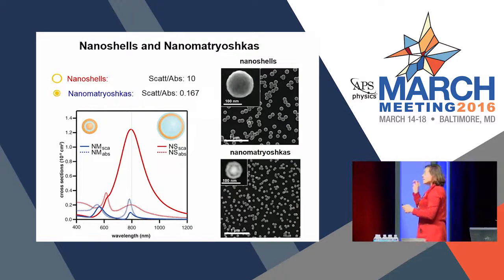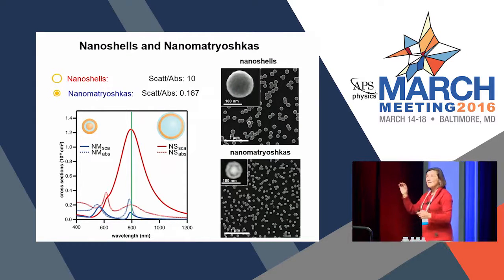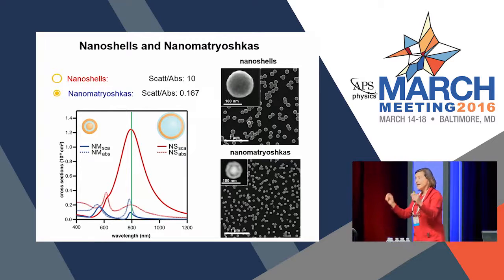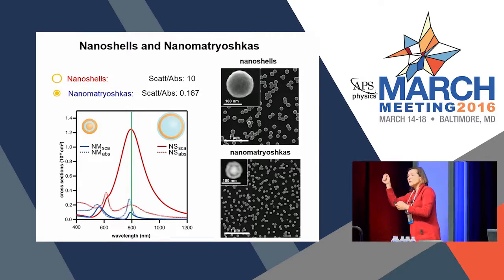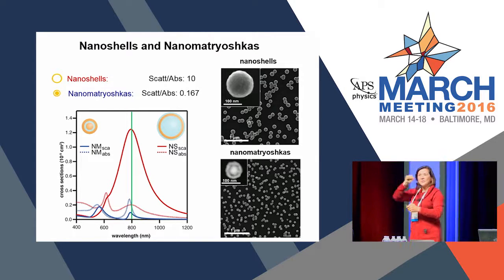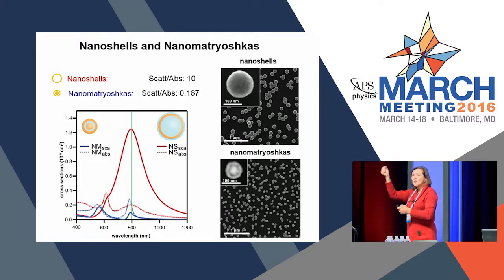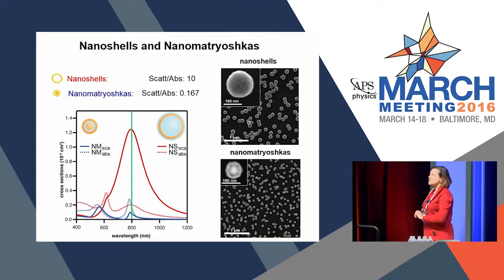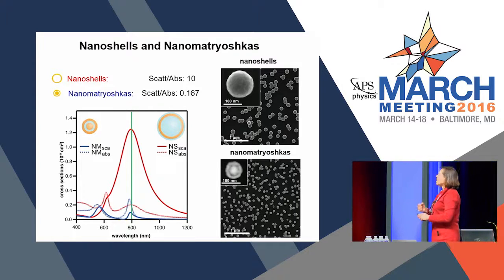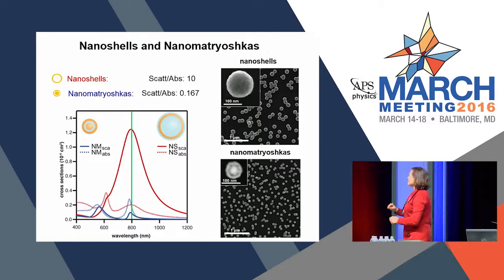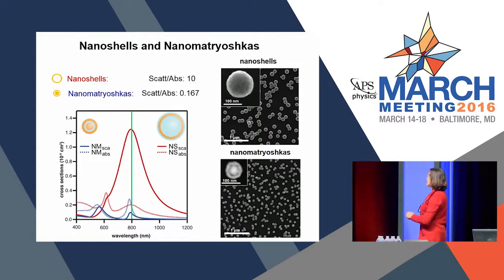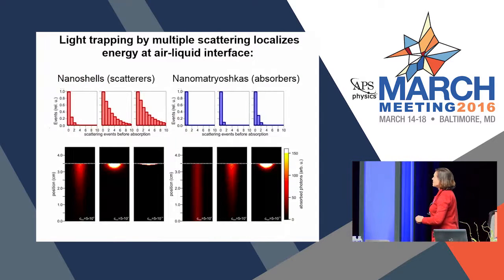To test this, we did a laser experiment, and we designed 2 different nanoparticles that had identical absorption, but depending on the properties of the particle, one particle scattered much more than the other. It was like we were tuning the scattering cross-section and keeping the absorption cross-section identical for the nanoparticles. These are the nanoparticles that we used, and these are the absorption and scattering cross-sections that I'm showing you right here. Nanoshells are one, and then we heard some reference to nested Russian dolls in the last talk. That Russian word is nanomatryoshkas, and these are plasmonic nanomatryoshkas, which are absorbers and not scatterers.